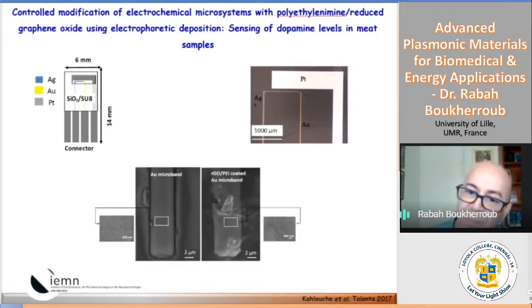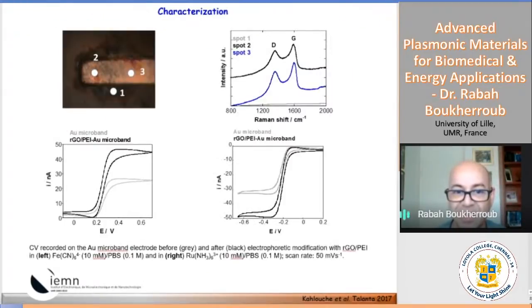And now if I want just to modify this, if I use drop casting, it doesn't work, because the drop will completely wet the whole surface and will modify the silver and the platinum. If I want just to modify the gold by applying the electrical field, you will see this electrophoretic deposition will allow me to selectively functionalize only the gold electrode. And you can see it here.